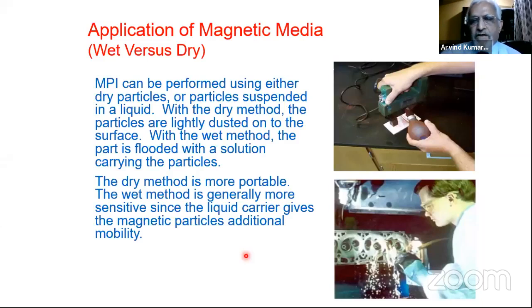So you should not be worried that there is a paint and over that they are doing MPI. Of course, if there is a painted surface, then again a demonstration is required. If the paint is up to 50-60 microns, no problem. If the paint is of more thickness, then what you have to do is take up a mock-up piece with the paint surface and an artificial defect, see that this defect is picked up under the paint, and then you can do the entire surface which you want to do, which is a painted surface.